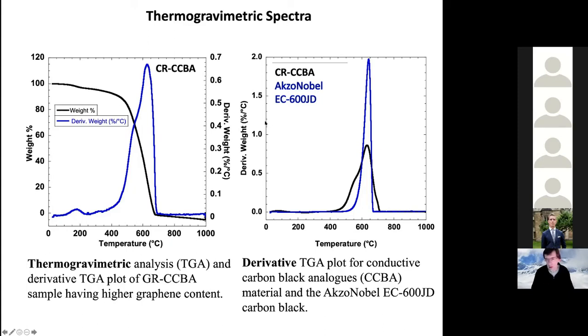The graphene is not shown here, but what is shown on the plot on the right is for AkzoNobel, a well-known commercially conducting carbon black. The product name is shown there, but by reference materials we can assign these peaks to the right form of the sp2 carbon, in this case the higher temperature peak being assigned to that of the graphitic carbon black analog, based again on the reference.